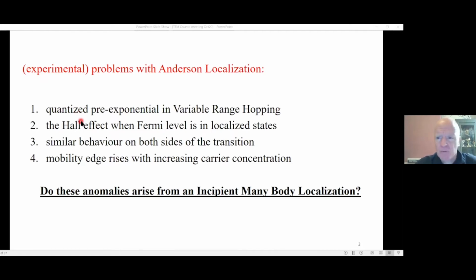The other problems which we've seen was when you have a Fermi level that's in a localized state, you have an activated conductivity. But if you measure the Hall effect, you get all the carriers. The carriers are not activated, which seems very, very strange. Also, the types of physics that we use to describe what's going on is very, very similar on both sides of the metal insulator transition.